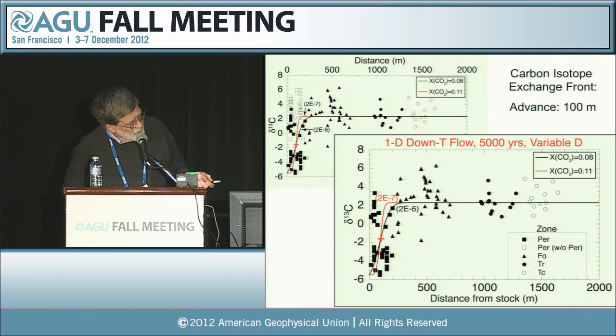But I think the important thing is that regardless of what curve you put through here, they're going to have high values of the diffusion dispersion coefficient. So the dispersion here is quite significant. In both of these cases, we've interpreted in previous publications that the dispersion we see in both the carbon and the oxygen front is the result of permeability heterogeneity introduced by bed-to-bed variations in the permeability. And we see that. I'll show you some information in a bit.